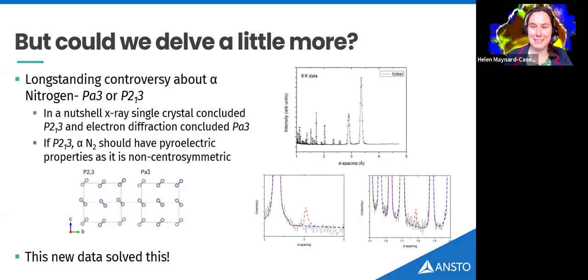It turned out when I collected this data, and I was quite surprised at how beautiful it was, that there was a long-standing controversy on the crystal structure. It's very subtle. It's around whether these molecules are actually centered on the origin. The prevailing structure had them slightly off-center to the origin, and the structure that I've proven it has to be is actually centered. It's quite important because if you have this uncentered structure, it imposes pyroelectric properties onto the nitrogen, which could have been very interesting, but unfortunately, or fortunately for Pluto, we found that it's actually the simpler symmetric structure.